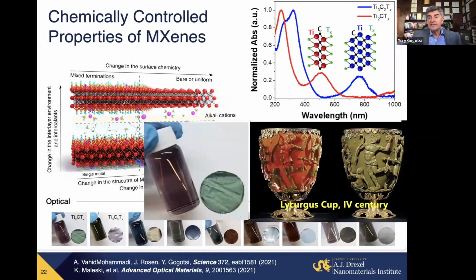Because depending on structure and composition, we will get different absorption spectra. Titanium 2C absorbs just like gold at about 550 nanometers. Titanium 3C2 absorbs at 780 nanometers. So it will actually be green in solution instead of red because of this. So I think the idea is here.